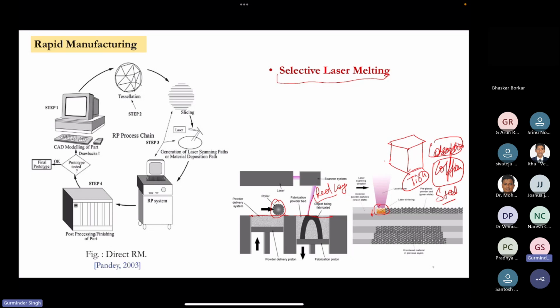But this type of process is very difficult for fabricating parts like copper, which has very high thermal conductivity, and silver, and pure aluminium. There are some grades like aluminium Si10Mg, which has 10% silicon, and it increases the absorption coefficient value of the material. But when you have to print pure aluminium or pure copper, it is very difficult with a red type of laser. You need very costly lasers like blue lasers or green lasers.